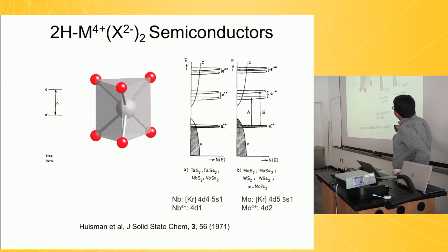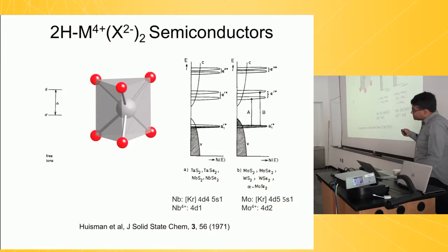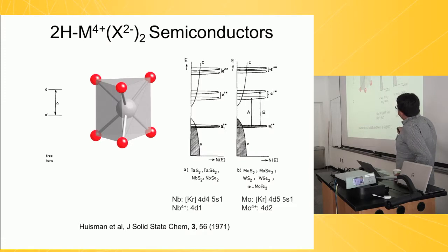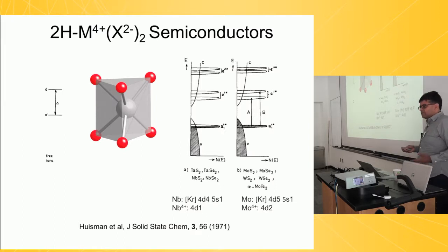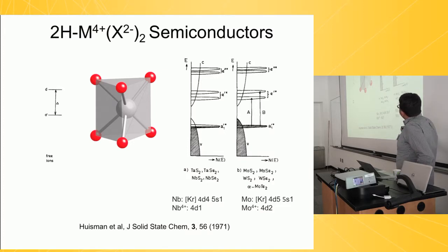I'm going to particularly look at the 2H form, where the metal atom has a triangle of chalcogen atoms on the top, and a triangle oriented the same way, the so-called trigonal prismatic version of these compounds. And if you take a metal ion and you put it in this coordination, just from symmetry principles, the d orbitals of the metal atom are going to split up into 1, 2, and 2 in this particular way because of the crystal field. And then you have to just ask, which metal atom do you have here to understand whether this material is a metal or a semiconductor.